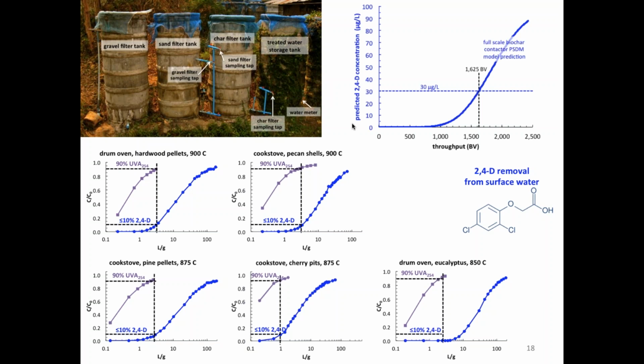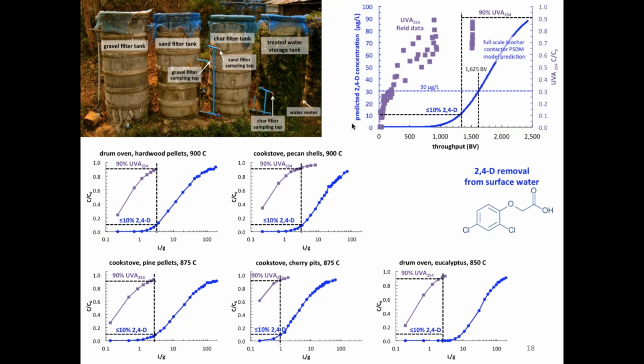We can use these breakthrough curves for 2,4-D that were collected in the lab, do that same mathematical transformation that I was talking about to predict what 2,4-D breakthrough would look like in this real world system, and then overlay the field data that were collected. These are actual field data from the full scale system of UVA adsorbents. You can see there's more scatter in the data because it was collected in the field over a couple of years. There are rainy seasons, changing water quality, and changing water sources. But we can roughly see that approximately this relationship of UVA breakthrough and 2,4-D breakthrough holds.